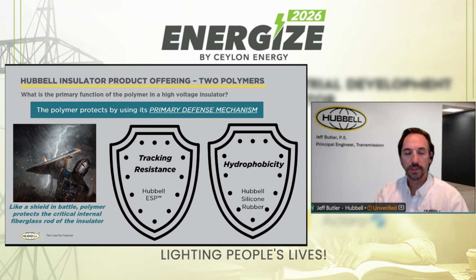On the other hand, when we're looking at silicone rubber, or specifically Hubbell's silicone rubber, the primary defense mechanism of silicone rubber is hydrophobicity, or the ability for water to bead on the surface, so that you're cleaning contaminants, reducing leakage currents, and reducing that electrical activity on the surface of the insulator. So while ESP is able to withstand that electrical activity, silicone rubber, while still durable, protects itself primarily through its hydrophobicity. But it is important to understand hydrophobicity is a characteristic of silicone that can decrease and increase and recover. And so we need to look at the life of the polymer even in those moments where the hydrophobicity may be lacking under high electrical stress.